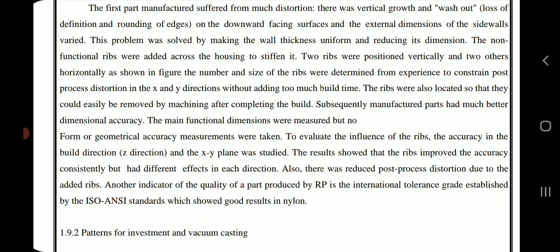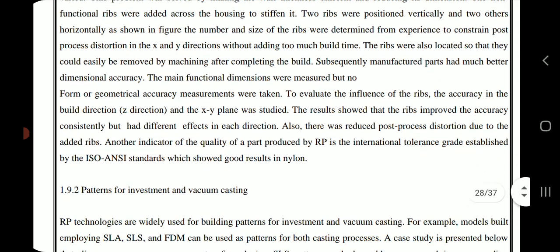The main functional dimensions were measured, but no form or geometry accuracy measurements were taken to evaluate the influence of the ribs. The accuracy in the build direction, z direction, and the xy plane was studied. The results showed that the ribs improved the accuracy consistently but had different effects in each direction. Also, there was reduced post-process distortion due to the added ribs. Another indicator of the quality of a part produced by rapid prototyping is the international tolerance grade established by the ISO ANSI standards, which showed good results in nylon.